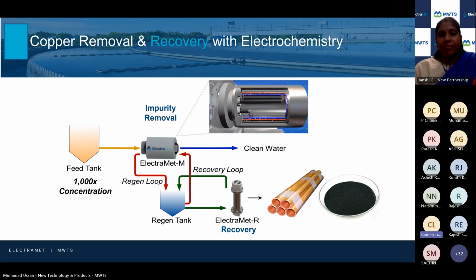And once the copper or other metals in the regen tank are high enough in concentration, we can implement an electrowinning type solution to recover these metals in high purity. We have now gone from what is typically a very dilute metal stream to a highly purified concentrate in acid, which is now perfect for electrowinning. And by doing this, we have a total closed loop solution to go from metals in the wastewater to a high purity value-add product. Next slide.